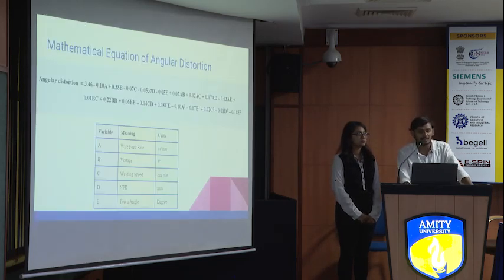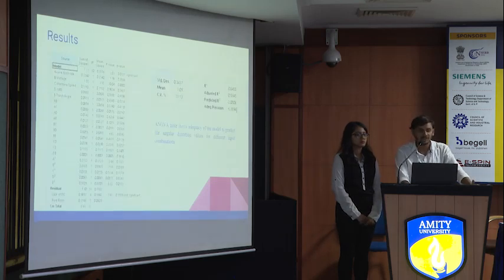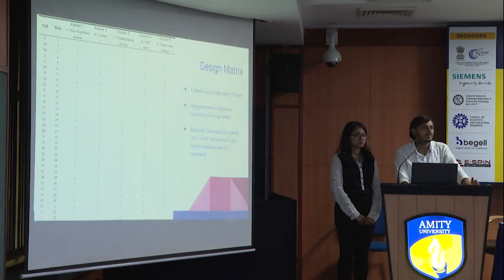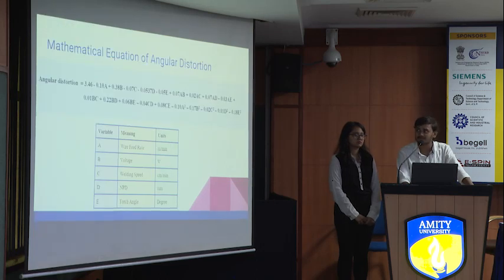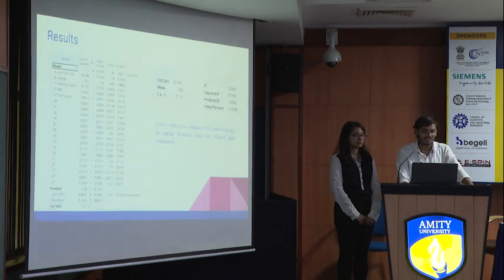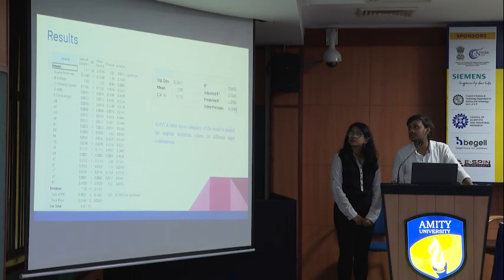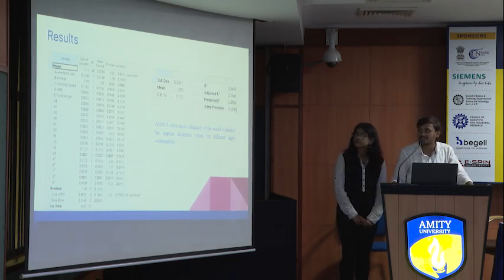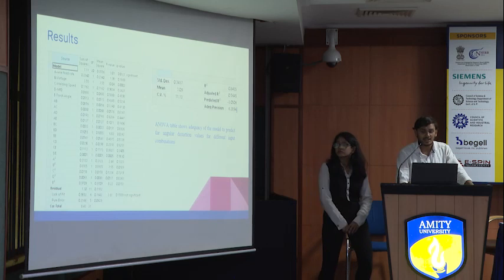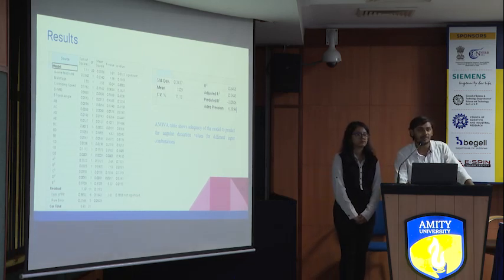This is the mathematical equation which, in this slide, we input the measured angular distortion, and from those values, a mathematical equation was generated. This is the mathematical equation which was generated by the software. These are the results. As you can see, our efficiency is 84.55%, which is significantly high. We use ANOVA, which is known as analysis of variance, to check the adequacy of this model.